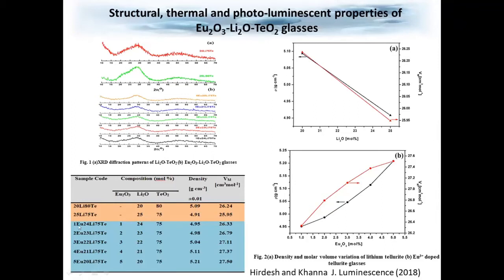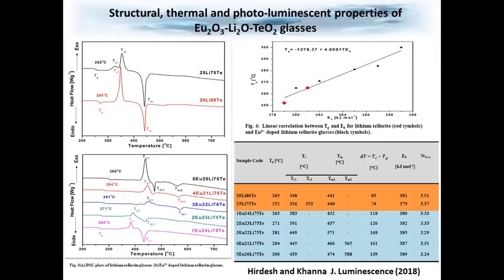We add europium ions at the expense of lithium ions. So when you increase the europium oxide concentration from 1 to 5 mole%, the glass density increases. The glass density is shown in the black dots, and the molar volume also increases. So when you add europium ions in the structure, the glass network is expanding. That is in a way beneficial, because it will prevent the segregation of europium ions, because if segregation takes place, then the probability of non-radiative transitions increases.